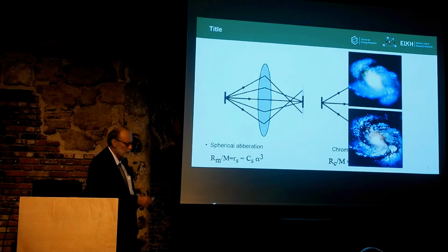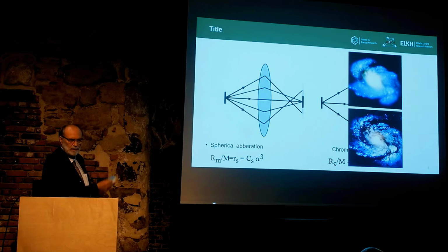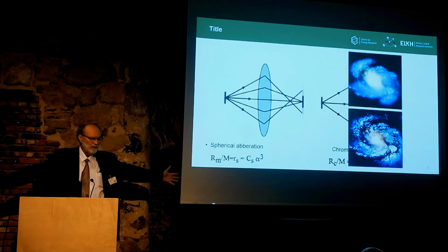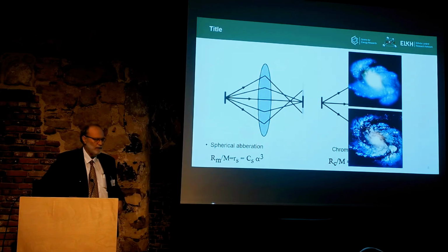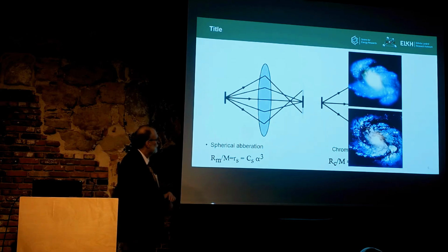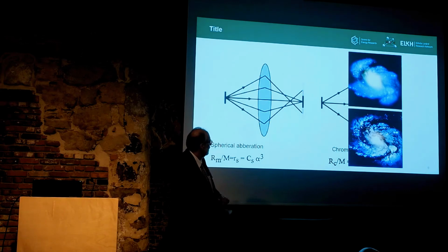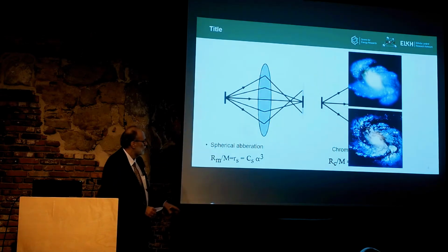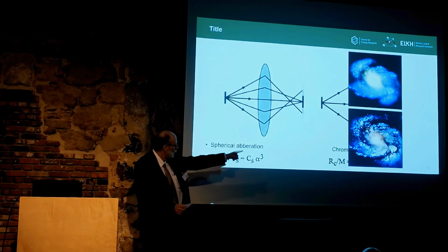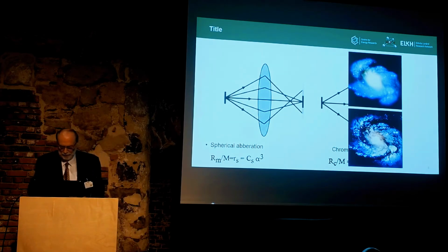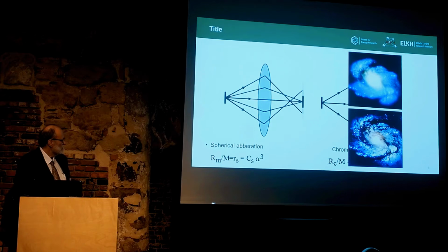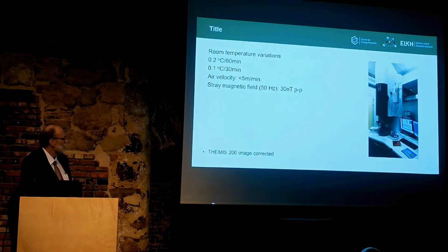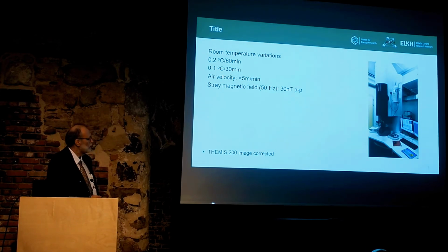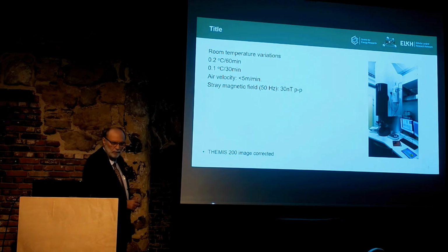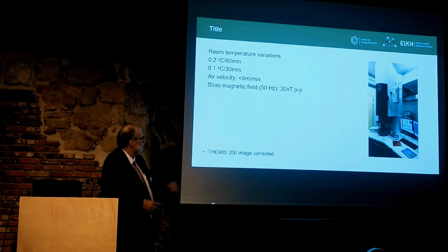So the image will not be so satisfying. And actually, 20 years ago, the same happened with the Hubble Space Telescope. There was a 2.5 meter large mirror, and it was launched into the sky, and they started to take images of the stars and space, and the above image was taken because they had this kind of spherical aberration. Later on, it was fixed on a second mission, and that image was taken. So if we can adjust the spherical aberration and make perfect lenses, then we can get far better images. On the right, you can see our microscope, which is getting old already, 3 years old, and it's the first aberration-corrected microscope in Hungary.